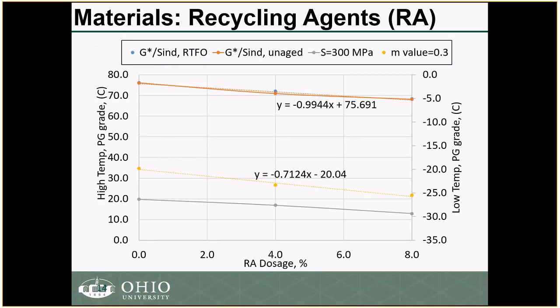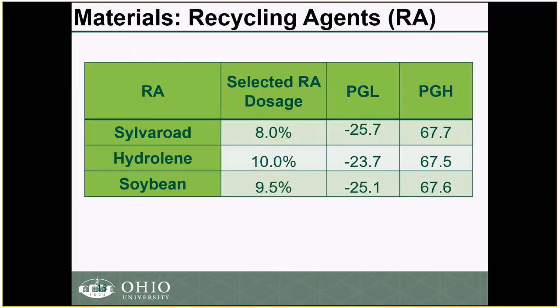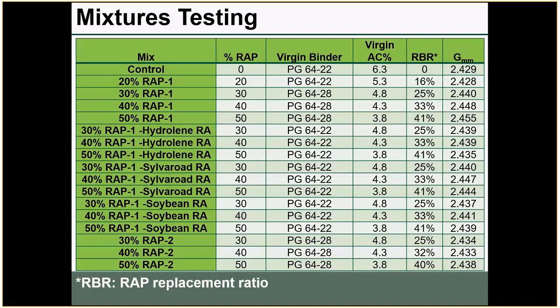And this graph shows some of the results that were obtained. Basically, the binder blend was tested at different dosages of the recycling agent, and based on that we determined the optimum dosage. And these are the results that we had for the different recycling agents, and you can see that the optimum dosage really varied depending on the type of recycling agent being used.